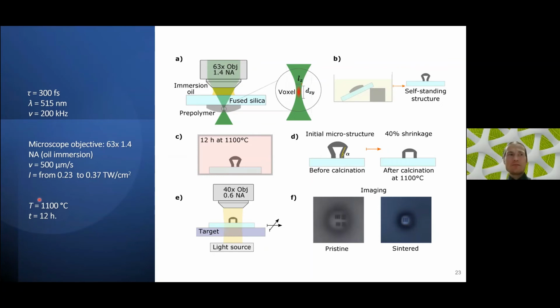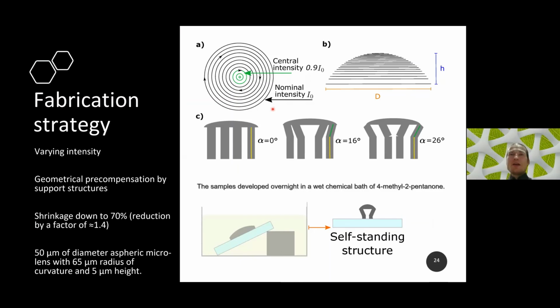And so again, high temperature post-treatment at 1,100 overnight from laser-made hybrid material. And then we needed to find a proper angle so that the shrinkage would be compensated. And in this case, it was something like a reduction to 70%, or by a factor of 1.4, for lenses of around 50 micrometers.